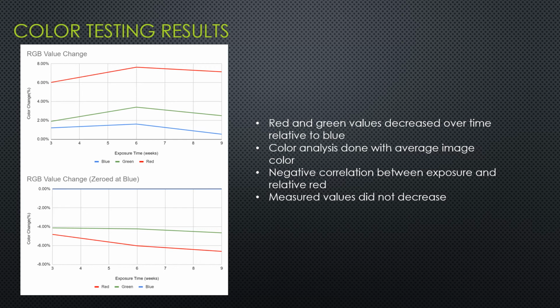When the values are zeroed at the blue, however, because blue is expected to have the least amount of fading, it's clearly shown that the red and the green decreased relative to the blue over time, with the red having the sharpest decrease. This is expected because red pigments absorb the higher energy ultraviolet and blue light while reflecting the lower energy red light. Absorbing these high energy light wavelengths cause the pigments to break down faster than other pigments of different colors.